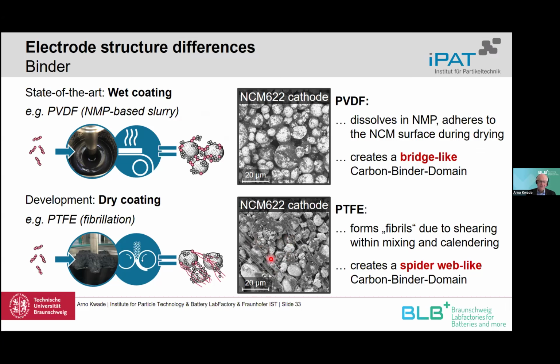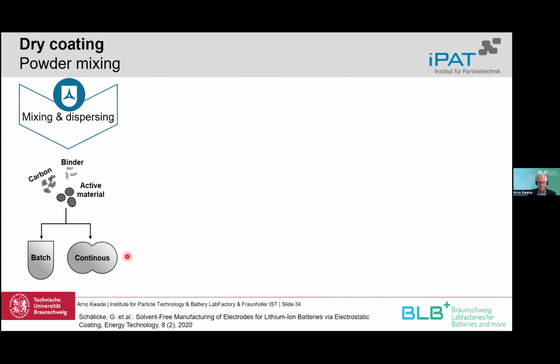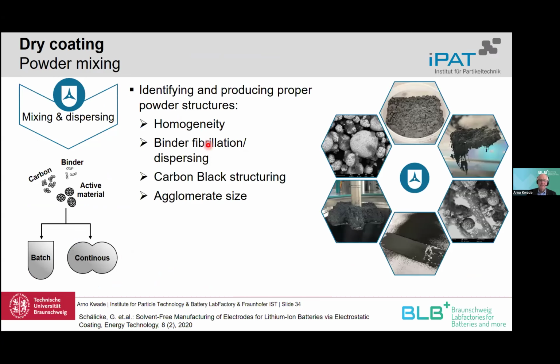And the fibrillation of the PTFE depends a lot on the mixing process. For example, in extrusion, you can have much smaller and shorter fibrils if you want. In a dry or a batch process, usually they are a little bit larger. But there's also, again, an optimum of length and thickness of these PTFE fibers. Now, this mixing process, as I just said, determines the binder fibrillation and also structures the carbon black. And it's important to say that in this case, the dry process has to do everything. There's no wet process, as I have shown before, that can do more work and you can finalize your structure. That has to be done here really during the dry processing.